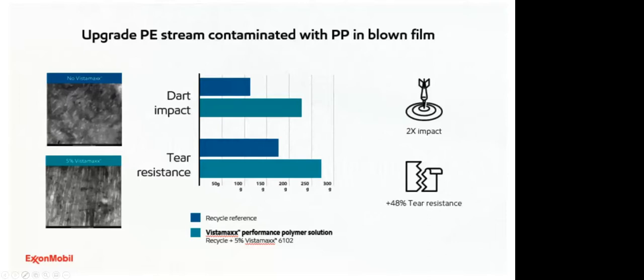In this next example, Vistamaxx polymers were able to upgrade polyethylene and polypropylene recycled streams to be used in a garbage bag. A blend of high-quality recycled polyethylene and 30% recycled PP as a contamination was turned into a 50 micrometer film. Some converters produce both polyethylene and polypropylene-based films, or multi-layer structures containing both polyethylene and polypropylene layers. These films are then recycled together without segregation. However, the two plastics will not mix together, which limits dealing with mixed waste and decreases the performance and therefore value of the recycled products.